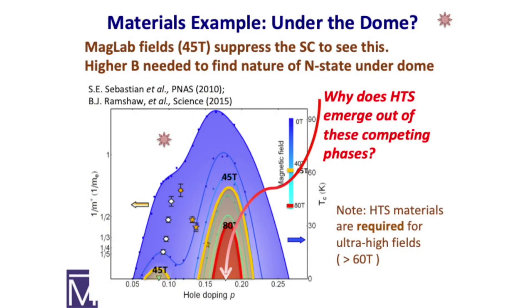Besides just trying to understand the fundamentals, we are going to go towards higher fields, and we are being funded to do that. If you want to go to a higher and higher magnetic field, you're going to have to use a cuprate. Right now, nothing else will hold those fields, not because the TC is higher, but because the field at which it can sustain superconductivity, the upper critical field, is that high in the cuprate superconductors.